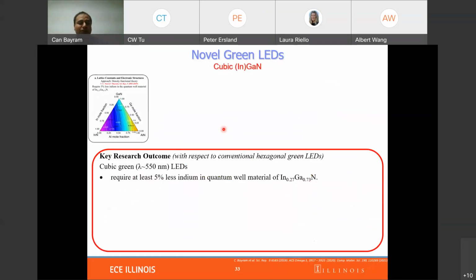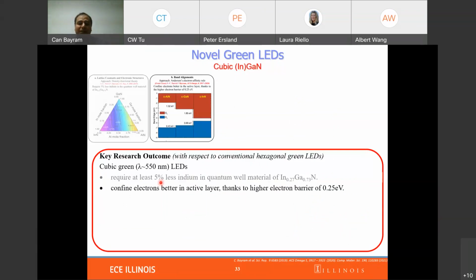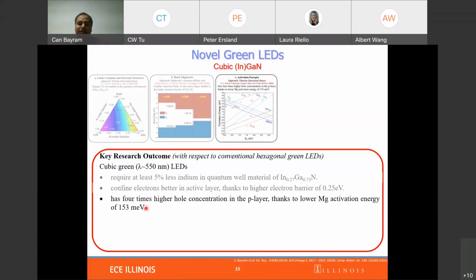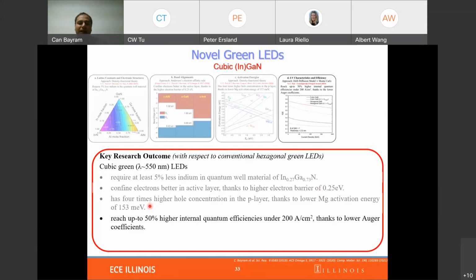Right now, we are looking into using cubic indium gallium nitride materials. Theoretically, we have studied many of these structures, and we saw that cubic nitrides require at least 5% less indium. They confine carriers better in the active layer because of the larger barrier. They can achieve higher p doping, and this has also been shown. And you can achieve much higher internal quantum efficiencies because of the lower Auger coefficients.